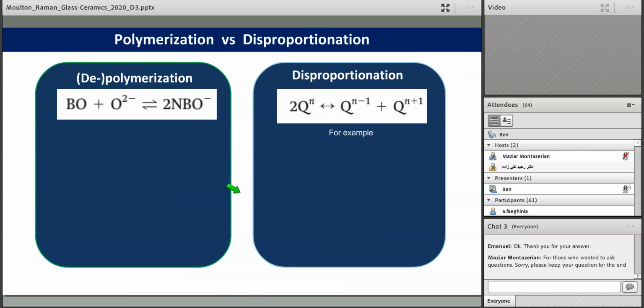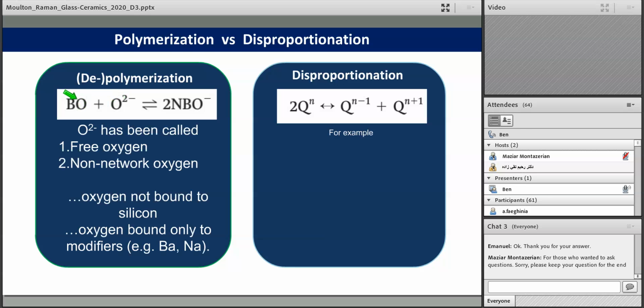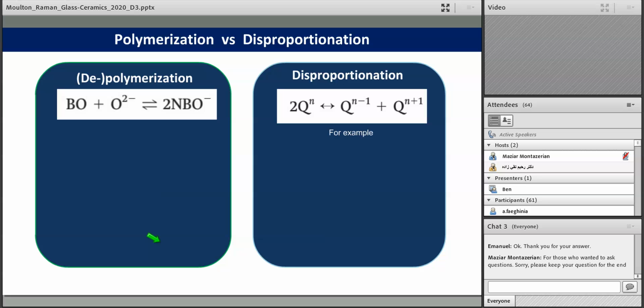If you've looked at this literature at all, you're probably familiar with two different equations. On the left is the depolymerization or polymerization reaction. Bridging oxygen breaking up into non-bridging oxygen is depolymerization, heading in this direction, and polymerization is when you head in this direction. In addition to non-bridging oxygen, there's a third oxygen species that I've introduced here, called free oxygen or non-network oxygen. It's not a radical oxygen, which some people confuse it with; it just means that it's oxygen that's only bound to our modifier cations here.